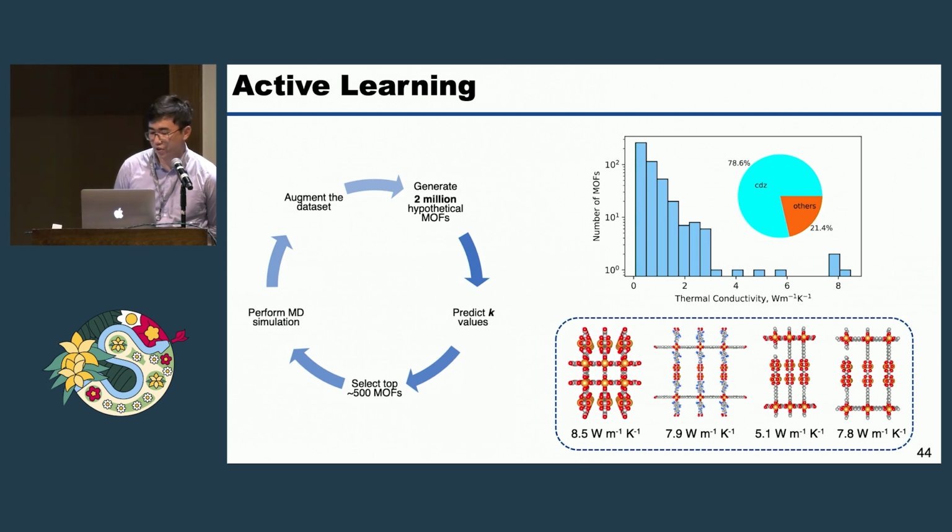Yeah, that's a very interesting question. Our lab has done many studies on that, and we also have experimental support. When the gas absorbs, the thermal conductivity decreases because of so-called phonon gas scattering. The kind of gas affects the vibration of atoms.